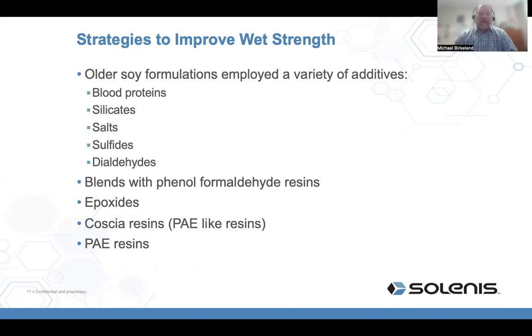There was a lot of work done blending soy with phenol formaldehyde resins. My opinion of that is generally that soy behaves like a filler. You certainly will get some dry strength out of it, some structure to the adhesive, but it doesn't really incorporate directly into the resin matrix. Epoxides and Coscia resins, just sort of pre-PAE-like resins, but effectively smaller molecular weight, but things that can directly react with side chains on the soy are also viable. And then most recently, and certainly important to Solenis, is the use of PAE resins. Next slide.